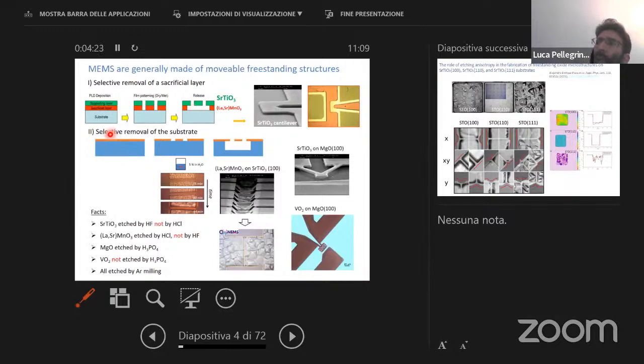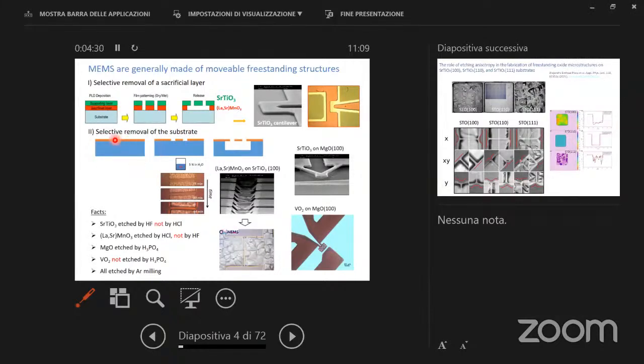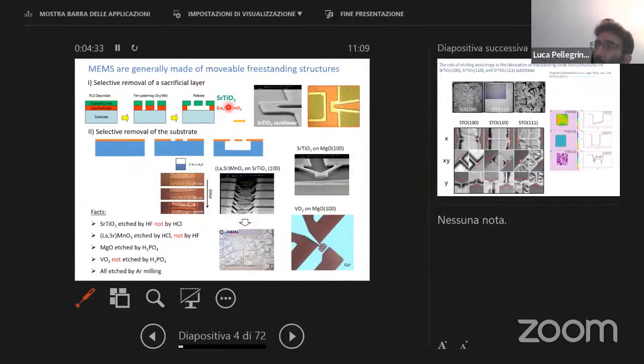Secondly, we can use a substrate. We can also remove the substrate, and this is a second example. Here we grow a manganite film, which is this one, on STO. In such a case, we can use fluorhydric acid, which affects STO, but does not etch manganite, LSMO. So we do patterning by photolithography, and then you can see in this image here that progressively the acid is removing the part of the substrate, and the light area here, the yellow part, means that the substrate underneath the microbridge is totally removed.